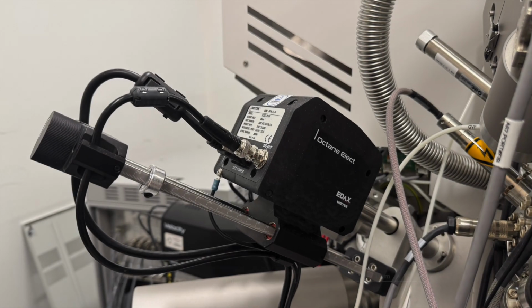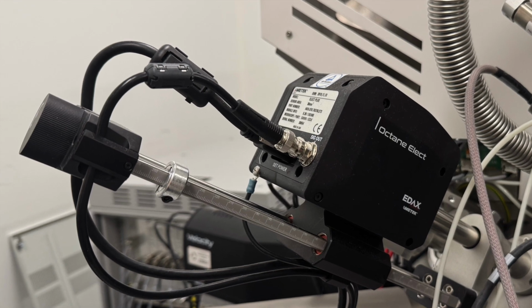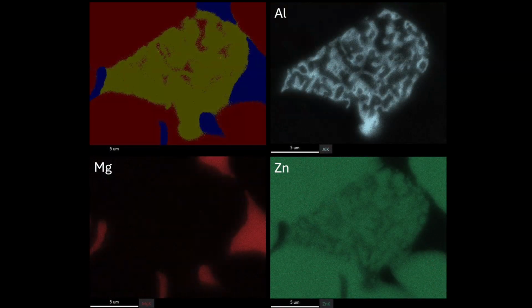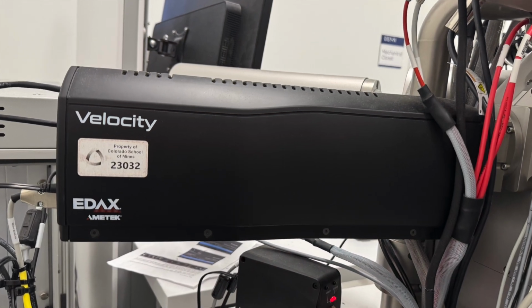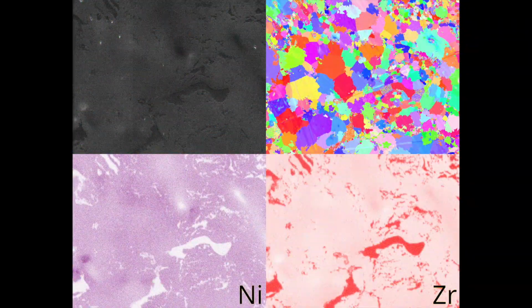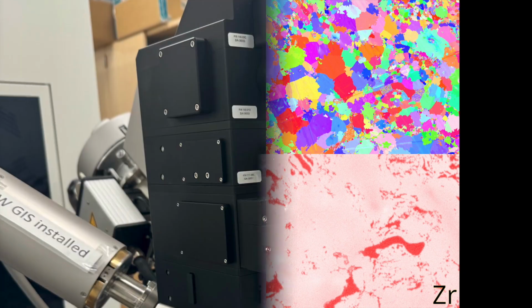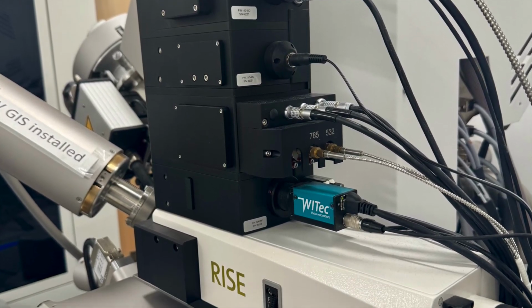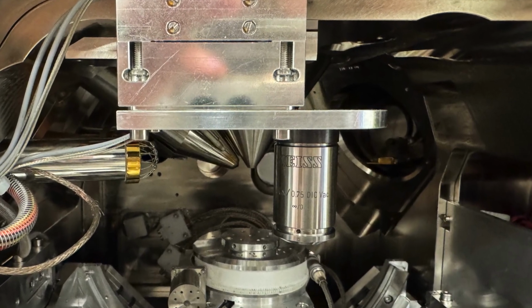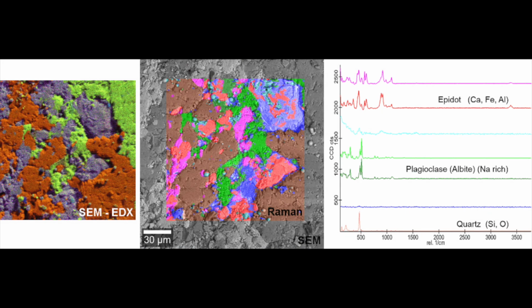For nanoscale compositional analysis, it features an EDAX Octane Elect Plus EDS system, powered by Apex software for accurate material characterization. The EDAX Velocity Pro EBSD camera delivers high-speed mapping at up to 2,500 points per second using a CMOS sensor. Paired with the EDS detector, it enables simultaneous compositional and crystallographic analysis. The instrument integrates WITec RISE confocal Raman imaging with 532 and 785 nanometer excitation wavelengths and 100 times objective, providing detailed chemical bond analysis.